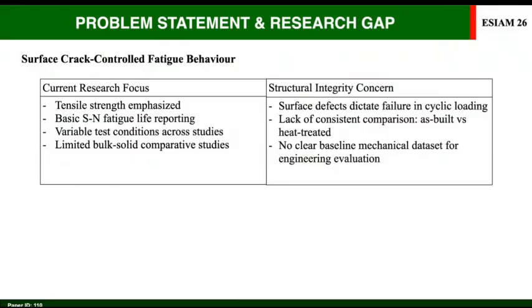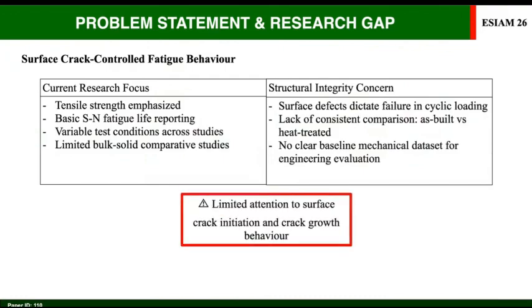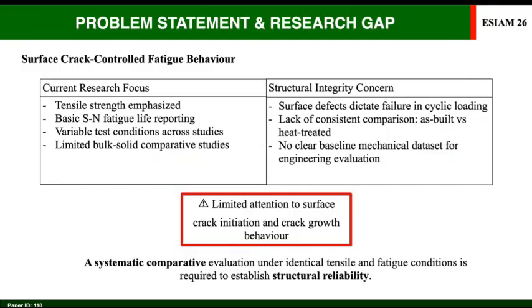Although extensive research has been conducted on DMLS-fabricated AlSi10Mg, most studies prioritize static tensile properties or simple fatigue life measurements. Additionally, differences in load ratio, specimen geometry, and testing frequency limit direct comparison between studies. Most importantly, limited attention has been given to surface crack initiation and early crack growth behavior. This is a critical oversight because in cyclically loaded components, failure is often governed by cracks initiating from surface defects or stress concentrations. Without understanding crack sensitivity behavior, improvement in tensile strength or hardness may provide a misleading indication of structural performance. Without a baseline, structural integrity assessment remains uncertain.